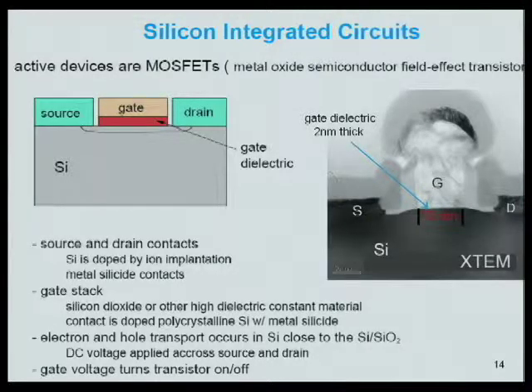The distance under the gate here is 70 nanometers. In the dimension going into the board, the device might be several microns. But the actual transistor, the actual current, is flowing in a layer that's about 5 nanometers deep underneath this gate. And what you don't see on the picture is the gate dielectric material, which is about 2 nanometers thick in today's devices. So we have nanoscale at least in two of the three dimensions of our transistors.